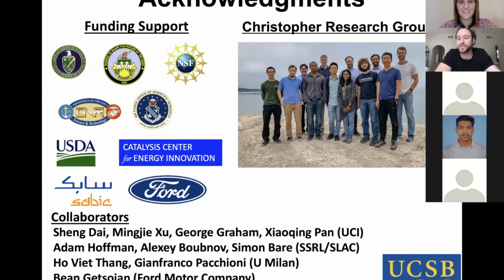Almost every case we've seen involves the support in some ways. If you're doing oxidation chemistries, we've typically done this using reducible metal oxides. And so you actually pull an oxygen out of the support and you do a redox cycle with the support. Hydroxyls on the support can likely participate.